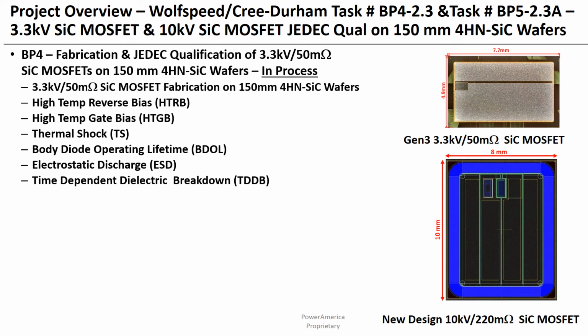In this presentation, we'll be first talking about the BP4 project, fabrication and JEDEC qualification of 3.3 kV 50 milliohm silicon carbide MOSFETs on 150 millimeter silicon carbide wafers. To the right, you see a die photo of the 3.3 kV 50 milliohm silicon carbide MOSFET, which has a die size of 4.9 millimeters by 7.7 millimeters. These were all fabricated on 150 millimeter silicon carbide wafers.